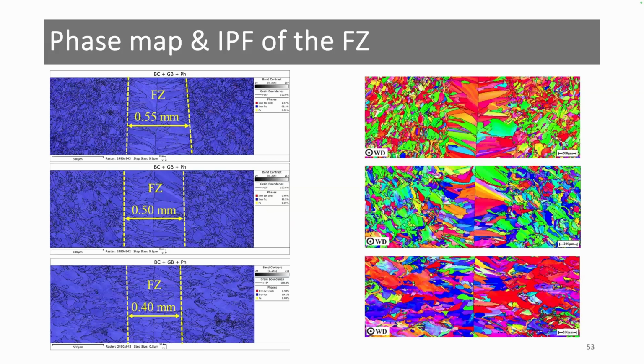And also you can see here that the size of the grains in the fusion zone are much greater than the size of the grains here in the 90 degree. And the main reason is that the orientation of the grain, which affected the cooling rate after welding.